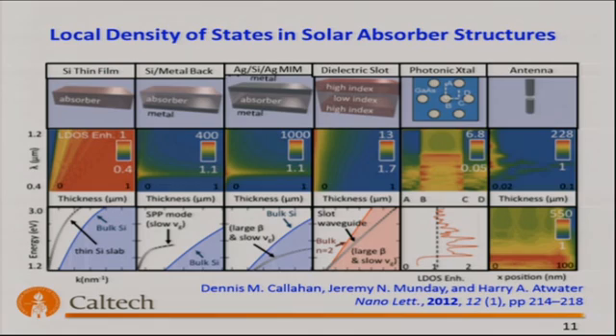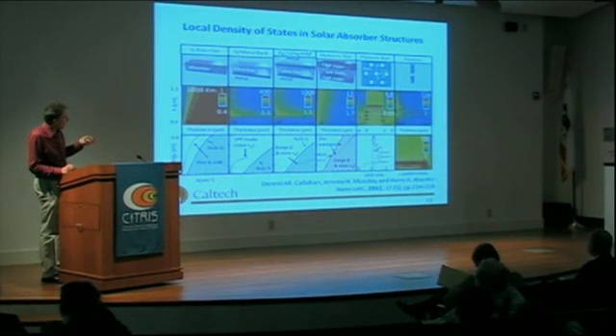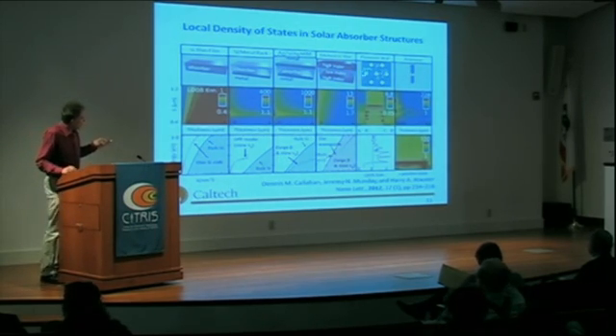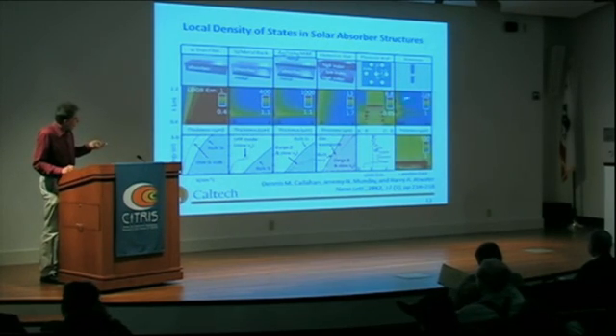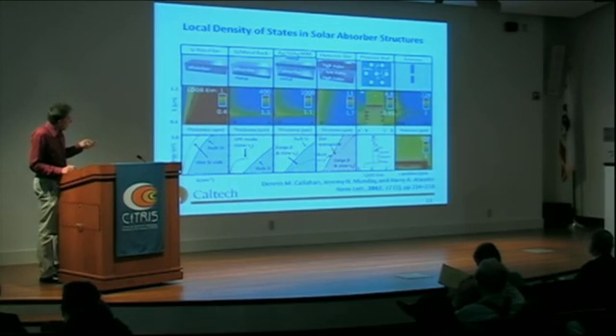But so you can say, well, okay, this is interesting, but it involves metals. Metals are lossy. Are there any dielectric materials that have this property as well? And indeed, you can also see this same sort of phenomenon with an enhanced local density of states for a low index medium clad by high index non-absorbing dielectric surroundings. You can also, for example, tailor the local density of states in photonic crystals and achieve considerable increases in the LDOS relative to a homogeneous bulk of the same material.